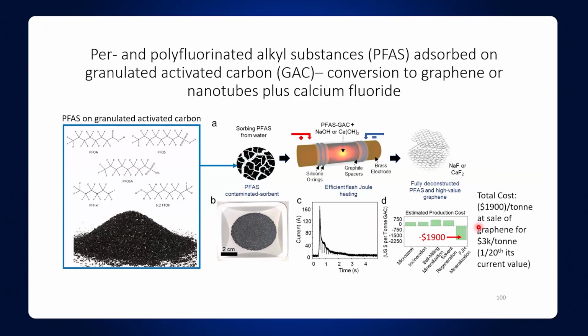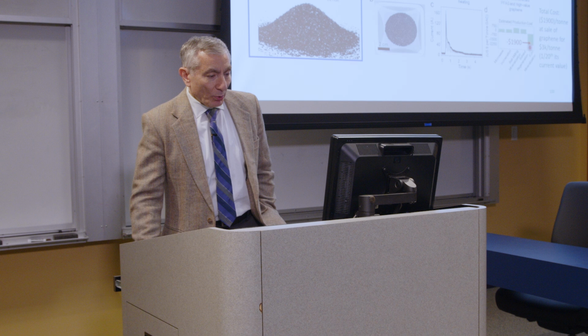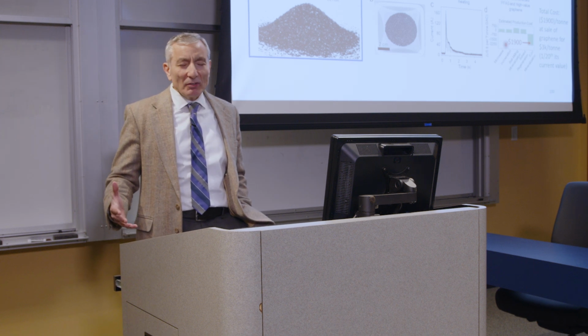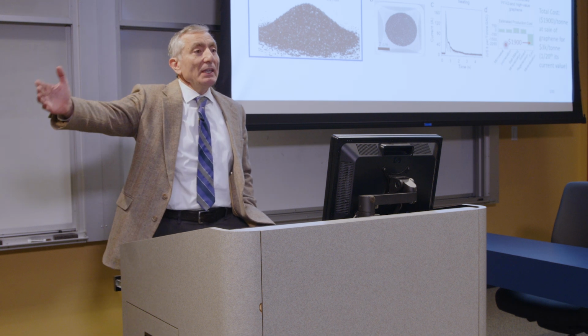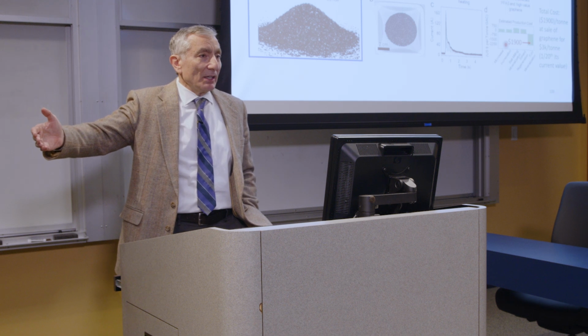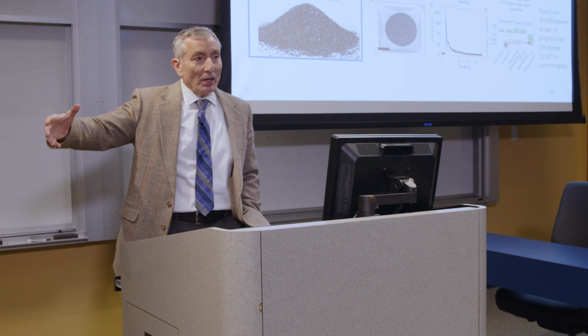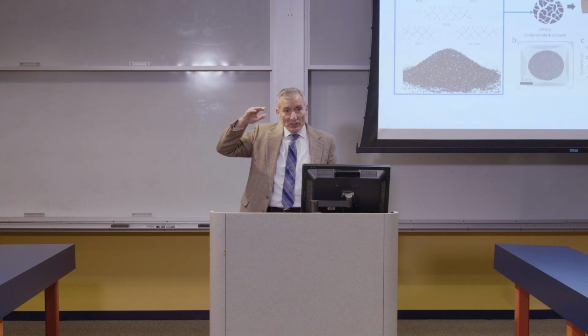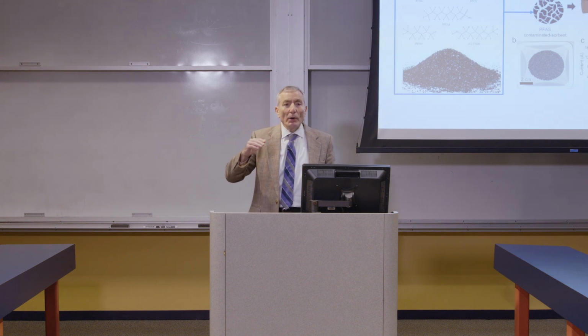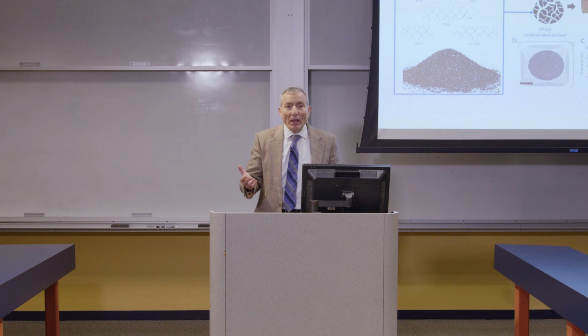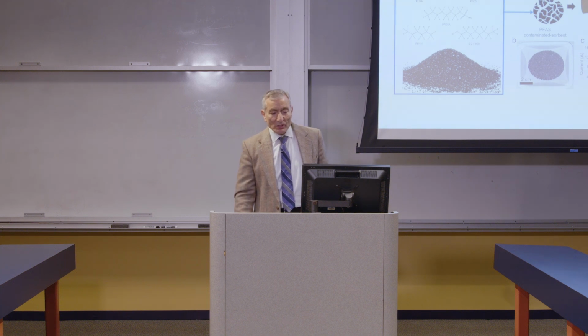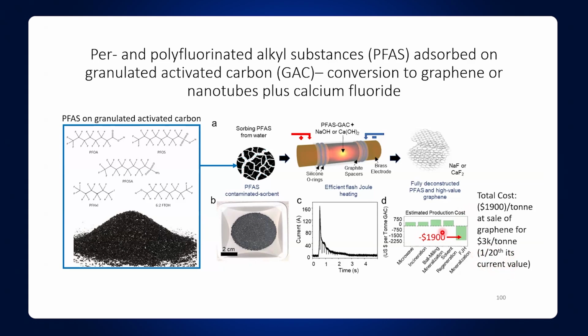And here's the kicker, because none of this is ever going to be used if it's not good on price. It turns out all the different ways of dealing with PFAS cost money. But this method is minus $1,900 per ton. You say, how can something be minus? I mean negative cost. Well, you sell the graphene. When you sell the graphene, you get all this excess money. Now, you say graphene runs $60,000 to $200,000 per ton, but we're not doing that. We're artificially, just on paper, lowering the price to $3,000 a ton, saying where might graphene eventually end up? The price of, say, a bulk plastic, $2,000 to $3,000 a ton. At $3,000 a ton, which is 1/20th of its current value, you're making $1,900 by doing this. So this is a great business.